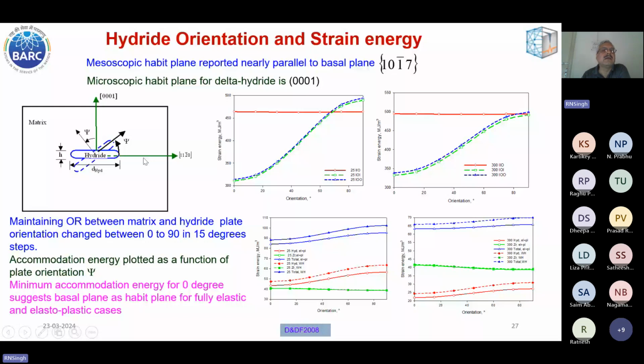At every 15 degree interval, we had the orientation, calculated the strain energy, and the plot is shown over here for the elastic case. You can see at 0 degree we have the minimum in strain energy, and as the angle with the basal plane increases, the strain energy also increases. So this suggests the common interface between hydride and matrix is the basal plane. This is again for the elastic case. For the elastoplastic case also, the results are nearly similar.